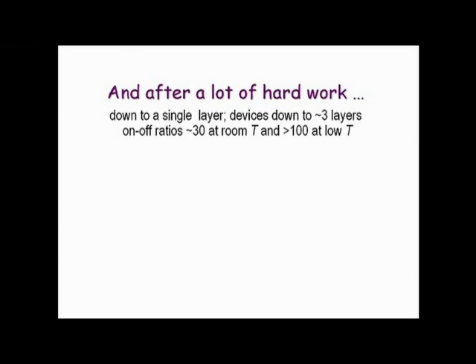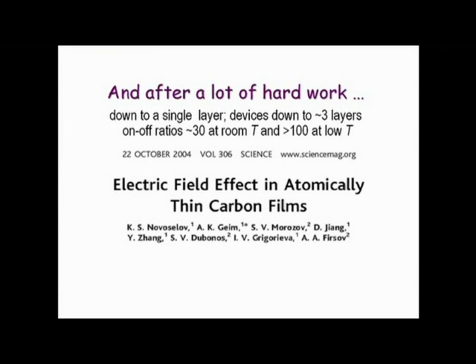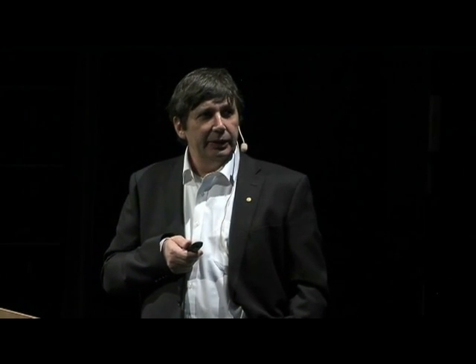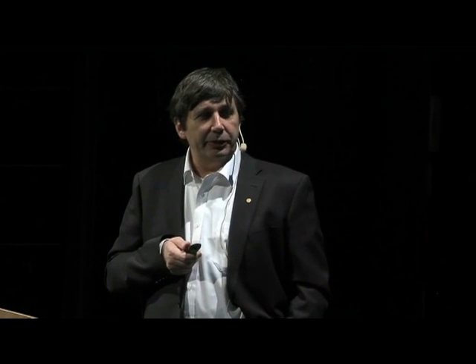What would we do if we make it thinner, use all the range of facilities which were already available at the lab? So we tried to push further and further, used electron lithography, went down to a single layer, and after a lot of hard work and plenty of experiments, a year later we published this paper cited by the Royal Swedish Academy. A remarkable thing about this paper was how hard it was to publish it.